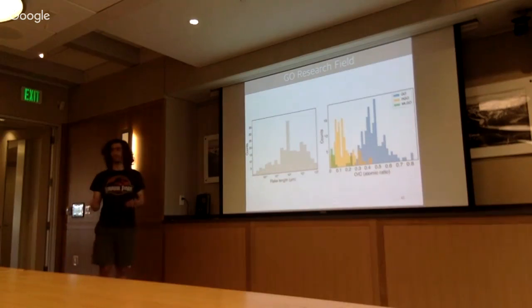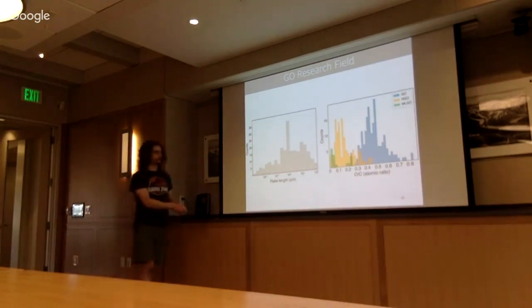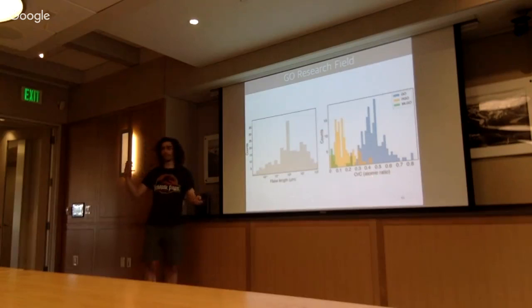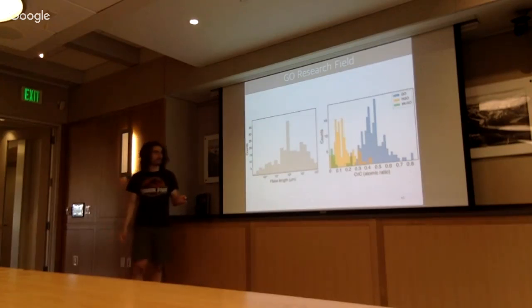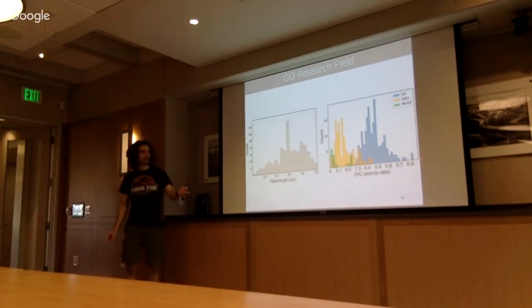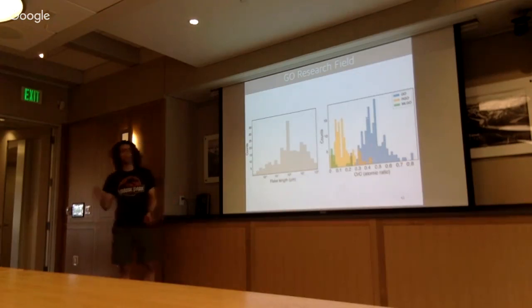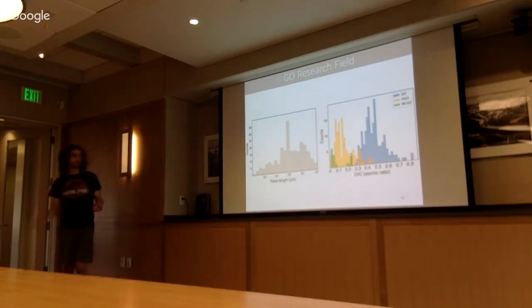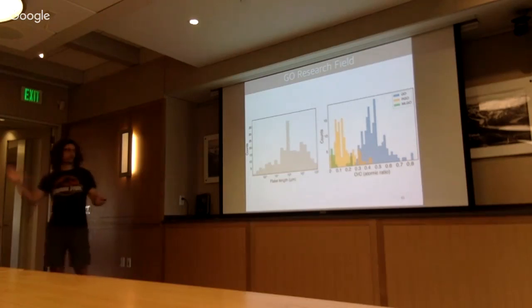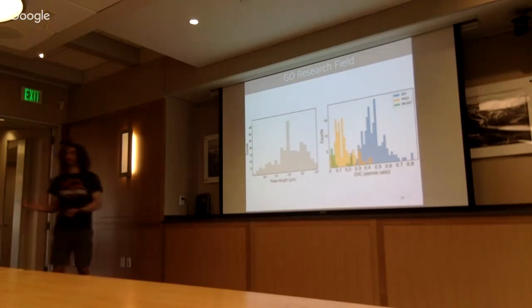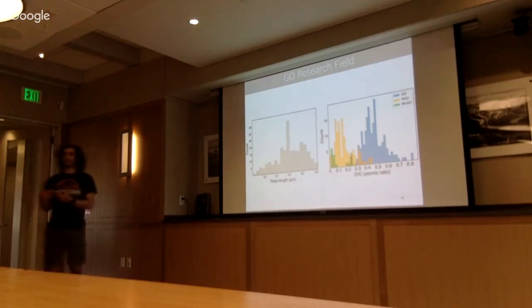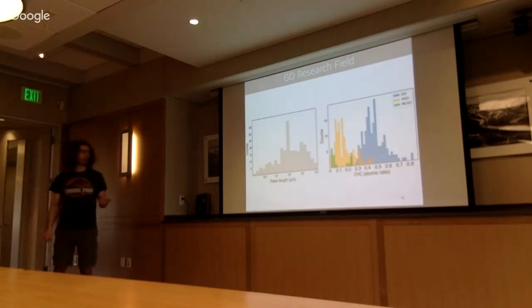Same thing for the chemistry. We have the oxygen to carbon ratio, which is a measure of the chemistry, so of the atoms inside the material. And we can see that graphene oxide in blue has a variation of the O/C ratio between 0.3 and 0.8. The mean is about 0.4 to 0.5. When we have reduced graphene oxide, there is a shift. And this makes sense because with reduced graphene oxide you are stripping some of the oxygen. And so, of course, you have a decrease of the oxygen to carbon ratio.